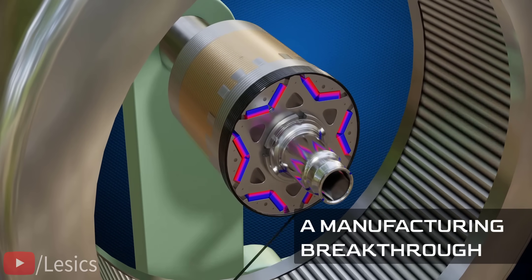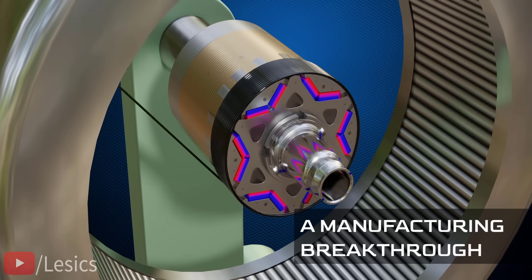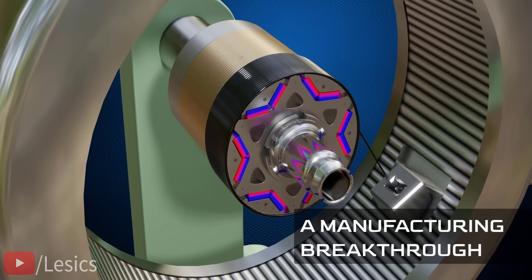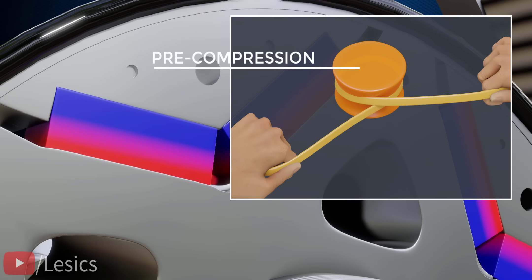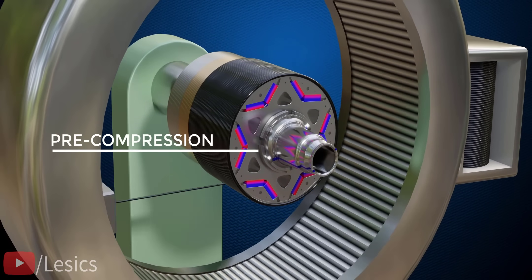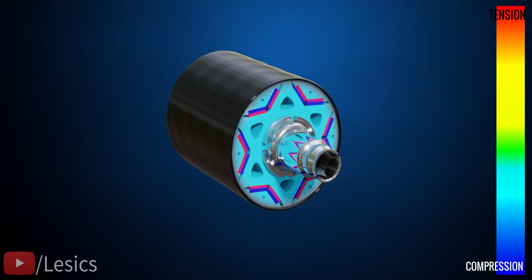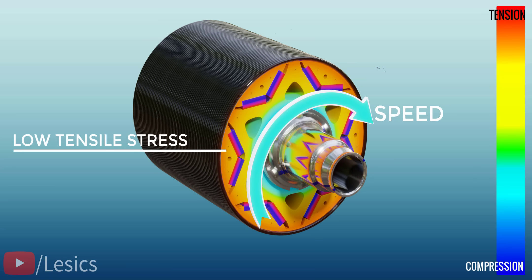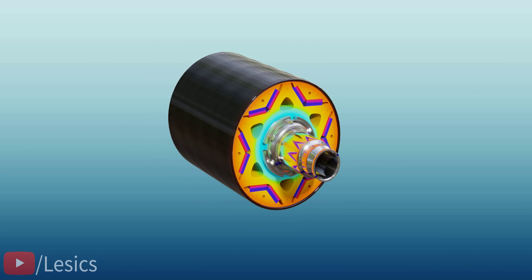We don't have much information about the full details of this engineering accomplishment. We know that Tesla developed an in-house carbon sheet wrapping machine designed to work on high tension loads — similar to an elastic band tightened around a cylinder compressing it. A similar kind of pre-compression happens in the rotor during the high tension winding. This pre-compression reduces the level of tensile stress at high-speed operation and saves the motor from material failure. Due to the support of this carbon fiber, the rotor can now have narrow bridges, improving the electrical performance of the whole motor.